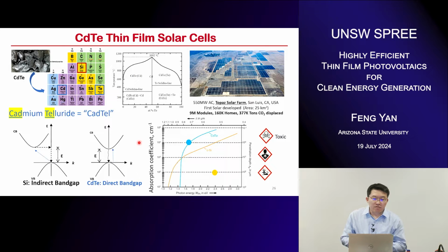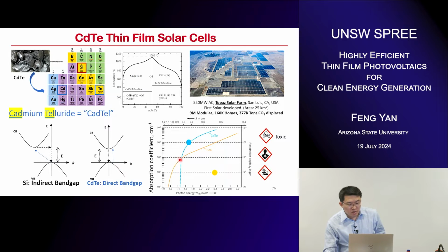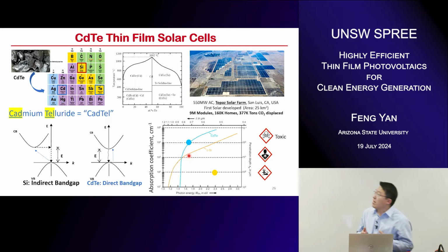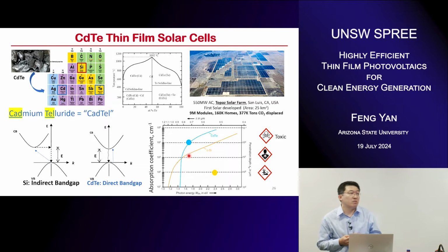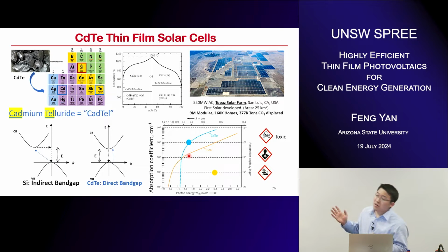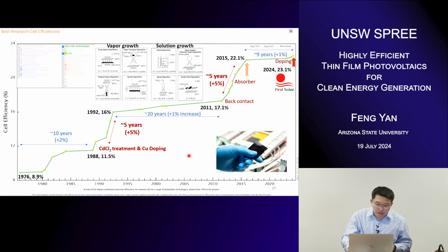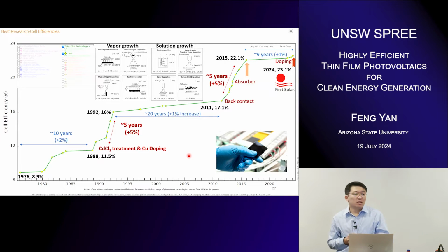We can see that several unique things drive this cadmium telluride technique. Compared to silicon, it's a direct band gap, which promises higher light absorption. The absorption coefficient is almost one order of magnitude higher than silicon. This is why cadmium telluride can be a very thin film, roughly 3 to 5 micrometers, whereas silicon needs around 100 micrometers. So this is very promising. Another thing is that many techniques have been used to grow this film, including physical vapor deposition and solution processes.